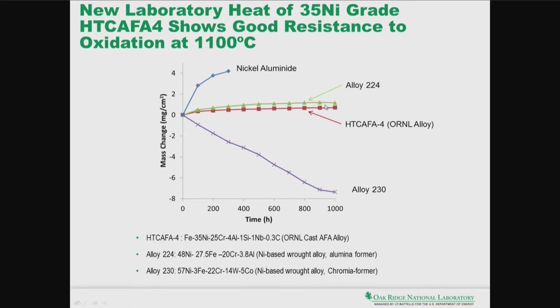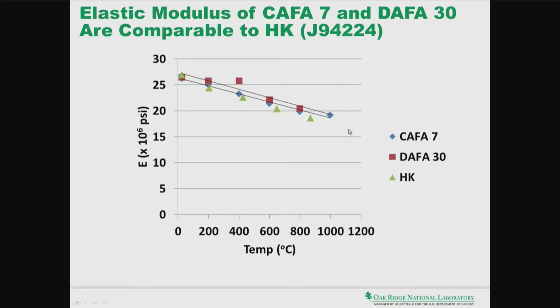And you can see how these two are tracking each other very well up to about 1,000 hours. And what is also shown here is an alloy 230, which is also a high nickel alloy, but it is a chromia-former. So clearly, again, the alumina-forming alloys come up on top, with good performance of the HTCAFA-4 at temperatures up to 1100 C. So clearly, we have shown you the data that illustrates the potential for oxidation resistance in these groups of alloys. And in the following, I'm just going to quickly run through some of the mechanical property data we have.